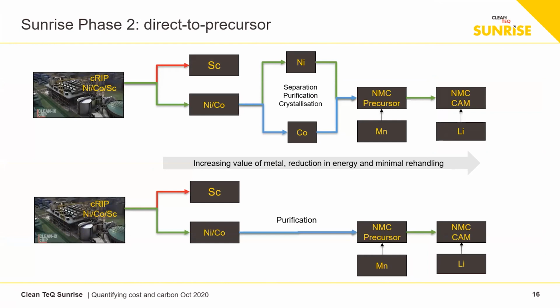Maybe one last point, I know time is short, but on cobalt, certainly in our engagement with the battery industry, at least in Europe, we are seeing very little desire to remove cobalt completely from cathodes for a couple of reasons. One is that the current cathode chemistries have got cobalt concentrations now to such a low level where it is not the biggest risk anymore to the cost of a battery. Nickel is by far the biggest risk to the cost of a battery today of all the raw materials that sit inside that cathode.